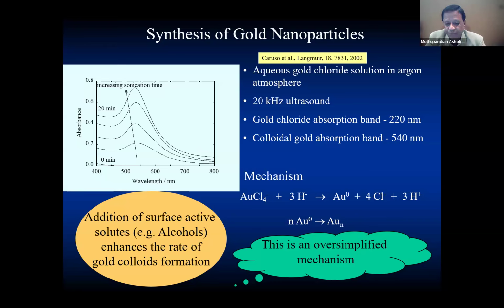The chemical reaction looks simple, but it is not an easy mechanism that I can explain to you. Simply, what we do is we take the metal salt in water. In this case, Au represents gold, so I'm taking gold chloride solution. And if I sonicate gold chloride solution, you can look at this absorption spectrum. Before sonication, I do not have any absorption in the range 450 to 700. As I start sonicating, I have an absorption band that appears around 530 nanometers. That absorption band is due to the plasmon absorption band of the gold nanoparticles.